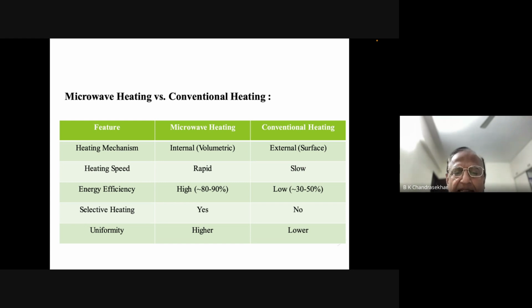As I mentioned earlier, that rate of heating can be as high as 300 to 400 degrees centigrade per minute, provided the sample can withstand it. Whereas in conventional heating, typically it is of the order of 10-15 degrees centigrade per minute. The energy efficiency is very high in microwave heating, almost to the extent of 80 to 90% in some cases, because only the sample gets heated and the surrounding crucibles, the insulating materials or any other thing is not getting heated. Therefore, there is a tremendous amount of energy savings compared to conventional heating.